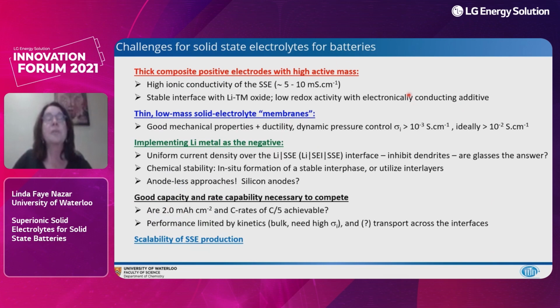So if we think about what the challenges of solid-state electrolytes are, well, they are many. First of all, we need a thick composite positive electrode with a high active mass, and that means we need to achieve high ionic conductivity of the solid electrolyte. As I mentioned, we have to form a stable interface with the oxide, and that means we need low redox activity with an electronically conductive additive, and that's a bit of a problem.